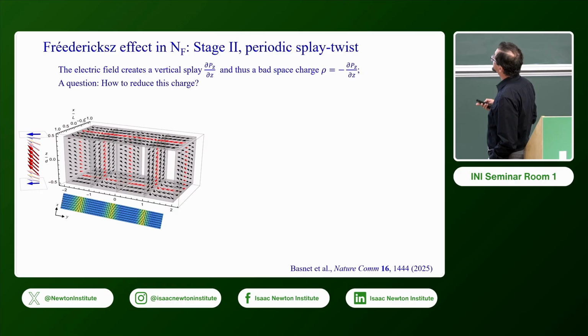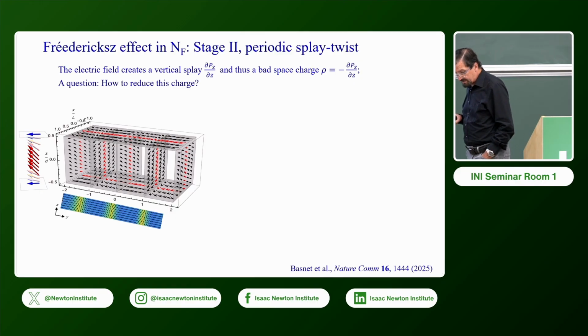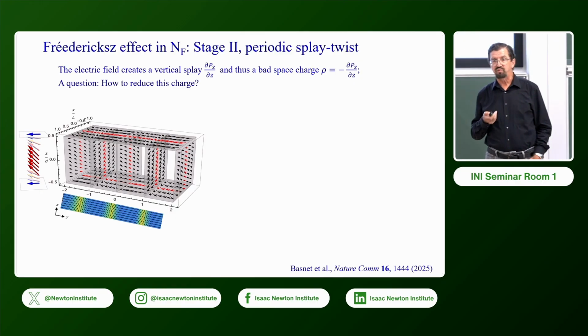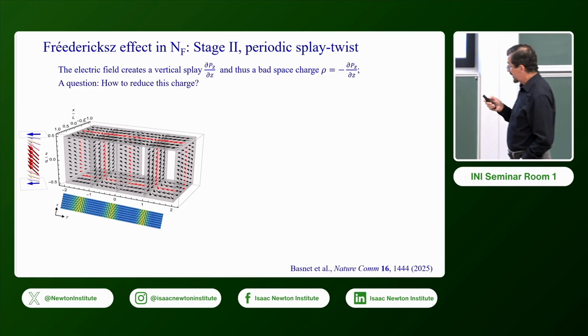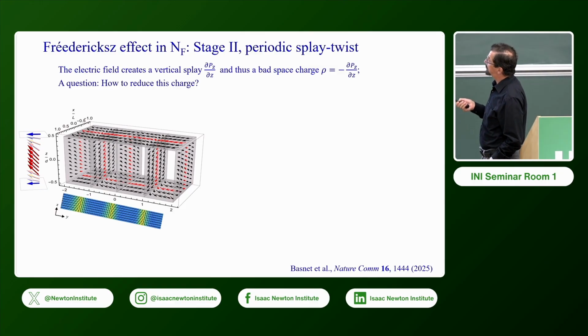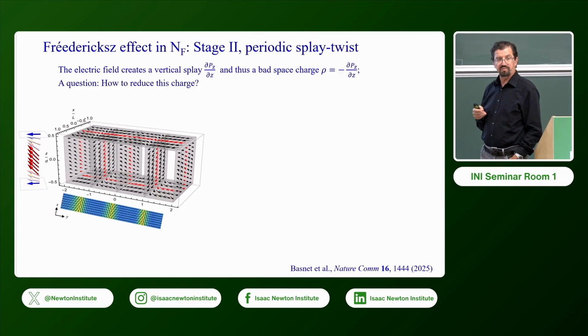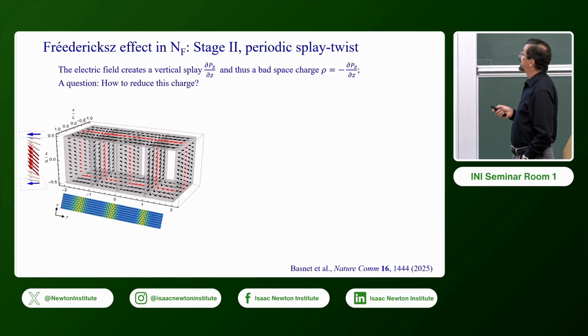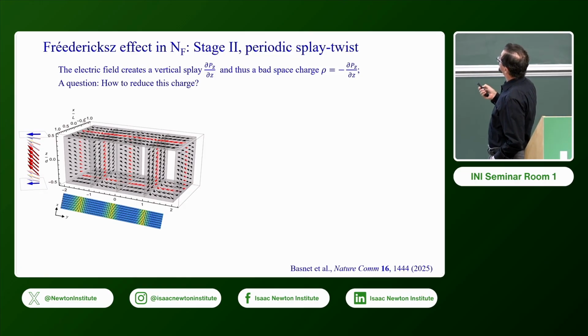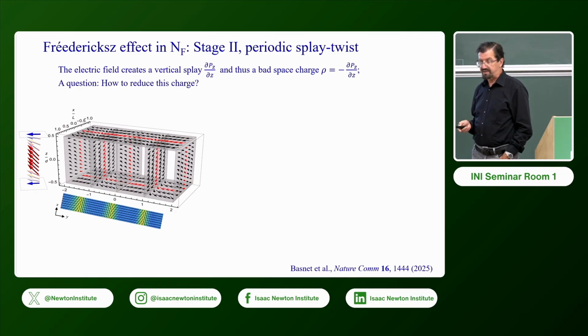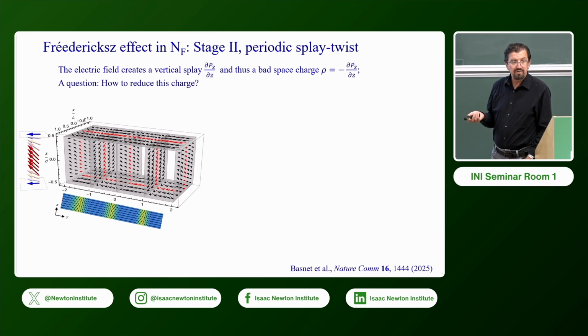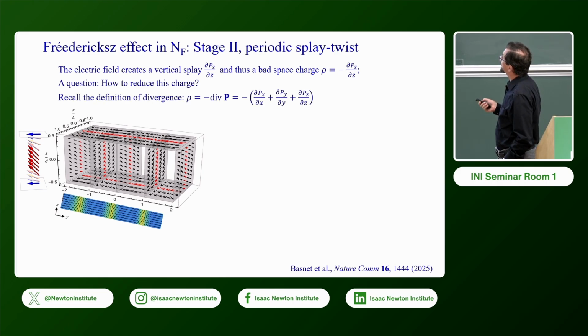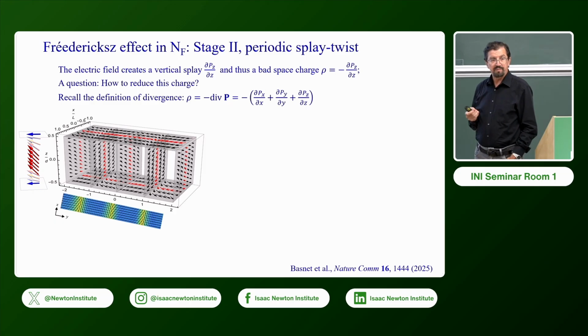And then you realize that the answer is in the tendency of the system to reduce the space charge. Remember, when we apply the electric field, we expect the two regions to be of splay nature, and that would create the space charge. The component of polarization along the vertical axis depends on Z, and that creates the space charge. How do we reduce the space charge?